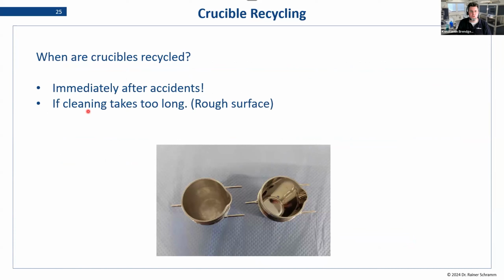Crucibles can be used for a longer time, but if there is an accident and you feel that it has been damaged, recycle it immediately. It's not worth the risk to your fusion equipment to use half-damaged crucibles. And in this case, this one will take a lot longer to clean because of the rough surface, and at some point it just becomes a nuisance. So if cleaning takes longer, like 10 minutes, that's a good sign to recycle them as well.